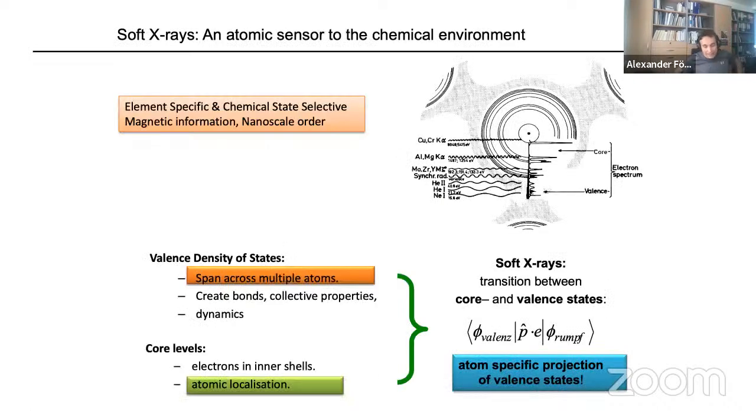Okay, that was the thing. X-rays are great. They allow us to differentiate different chemical species in spectroscopy. We understand that the analysis, what it means, can be either done on the Z+1 or equivalent core approximation, or it is being done in computational tools like Gaussian, Orca, you name it, where you use the Slater transition potential approach of half-filled core levels, which is a great way to computationally effectively mimic the situation of a transient core excitation.